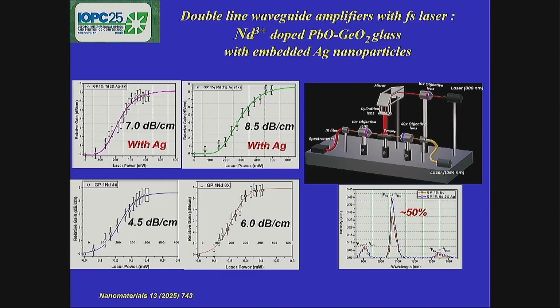Again, we determine the relative gain by using a similar setup. The only difference is at the entrance. Now the light of the signal is coupled to the glass in a different way, without using that lensed fiber but an objective lens. And here I show you results for the relative gain for samples with and without silver nanoparticles. Of course, we had to prepare those without silver nanoparticles to be used as reference. And hence, again, an enhancement of about 50% correlated to the photoluminescence increase, attributed again to the plasmonic effects of the silver nanoparticles.